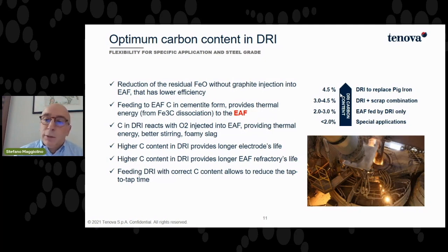So with this high carbon DRI, we can complete the perfect reduction of the remaining FeO. We have an additional source of energy by putting carbon in the furnace. And above all, we have the perfect foamy slag and the perfect process in the furnace, achieving longer electrode life, longer refractory life, and higher productivity by reducing the tap to tap.